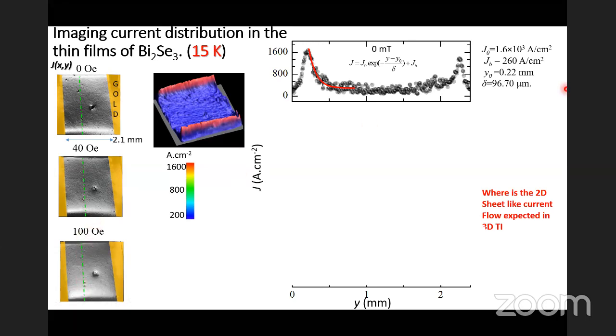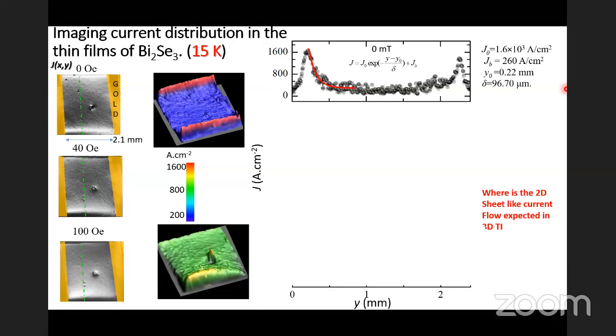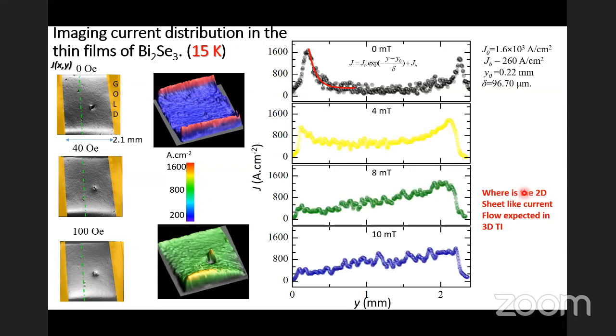This is quite amazing, that we could see the current distribution become almost uniform across the sample, with slight non-uniformity along the edges. From a non-uniform current distribution, with slight application of magnetic field, we actually start getting an almost uniform distribution. You can see that this peak at the edges decreases as you increase the magnetic field, and then you get almost a flat top current distribution across the sample. But this is in the thin films; you have to apply a weak amount of magnetic field to actually get this sort of a 2D sheet of current to flow inside the sample.